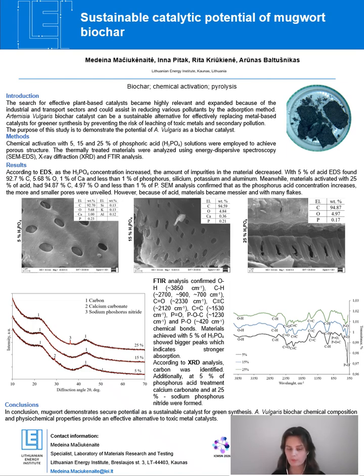It indicates that the bonds are attributed to hydroxyl, carbonyl, aromatic, aliphatic, phosphoryl, and phosphate ester groups. Materials achieved with 5% of acid showed bigger peaks, which indicates stronger adsorption. Of course, it reflected EDS results where the highest amount of phosphorus was found in the sample with the same 5% of phosphoric acid. It was a very interesting notice because it can be explained that this sample was the one with minimum amount of washing because 5% of phosphoric acid was a weak acid.